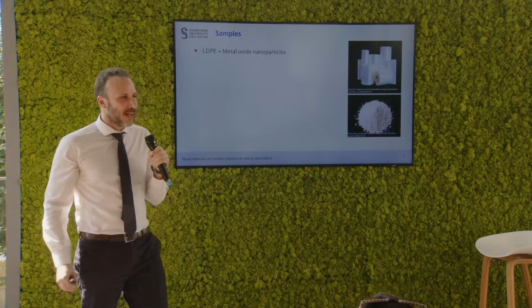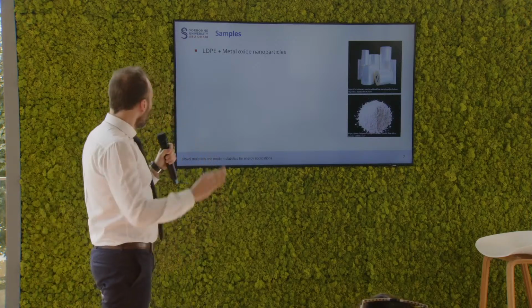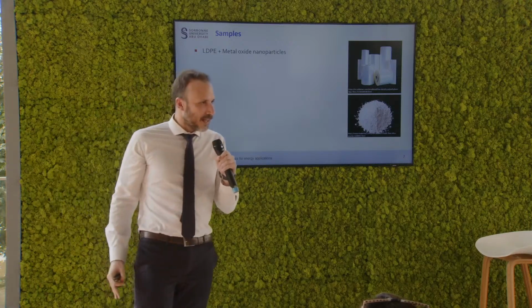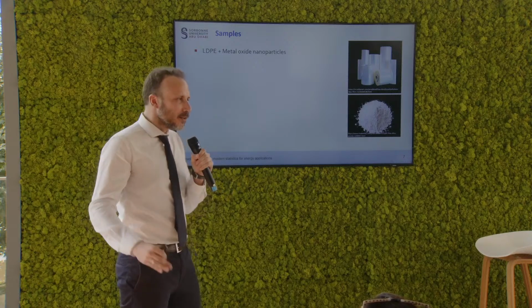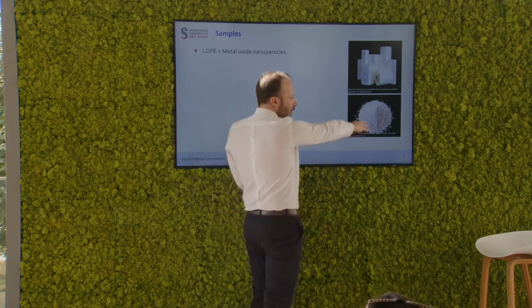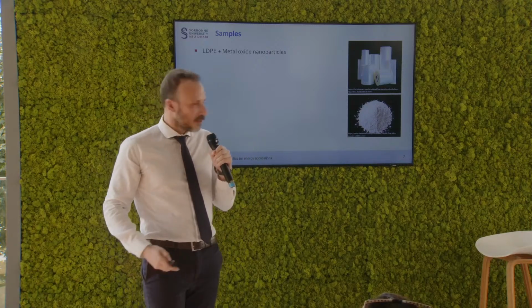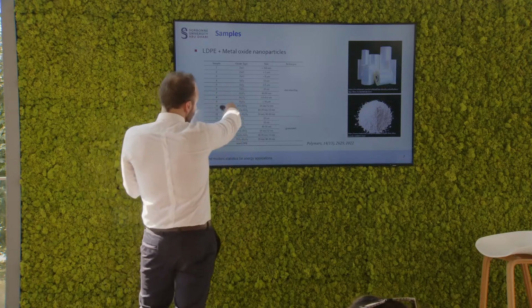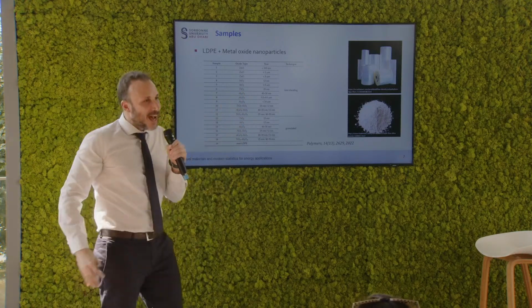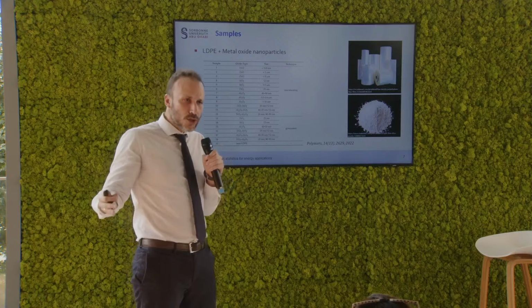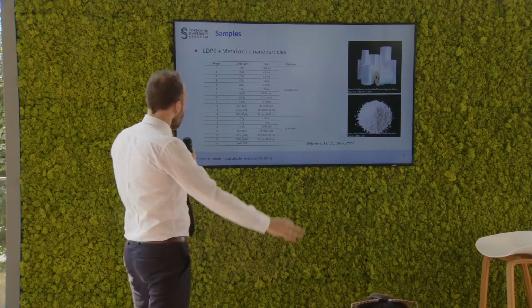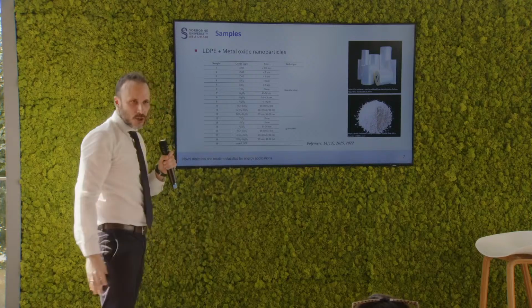So what we're going to do today, to show you the research that we're looking at, is we're mixing 2 basic things. The one is a polymer matrix, which is low-density polyethylene in our case. It's for a proof of principle mainly. And in that, we're going to embed nanoparticles of different types and sizes. The nanoparticles initially come in a form which is shown over here, a powder form. So just indicatively, so you understand what we're working with, we have zinc oxide, silica, titania, alumina as unary suspensions, but we also have heterogeneous combinations, which you can see over here, Ti-Si, alumina-Si, and so on and so forth.